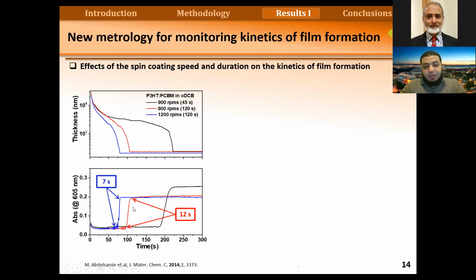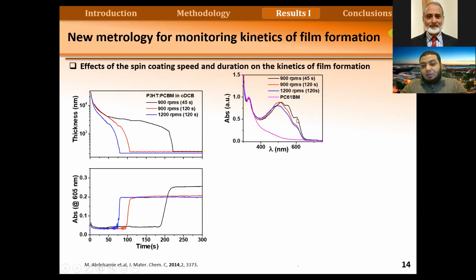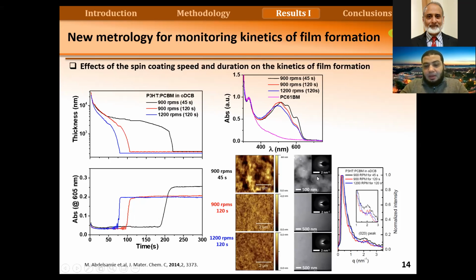And what we observe here is that we have differences also in the formation dynamics. We have a much longer time for the black curve here, which also has implications for the final state. We can see the black curve has high vibronics. This is an indication of high crystallinity of the film and high aggregation in the final film. We can also see the morphology by TEM and AFM. For the case with the longer dynamics, we can see larger domains of the donor and acceptor materials, and this is improved phase separation. So this material can have a better performance.